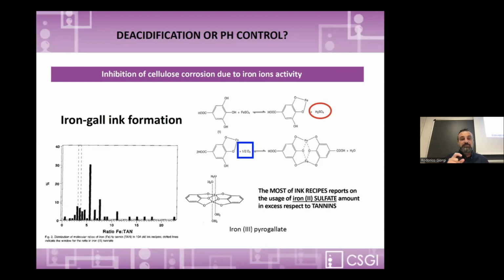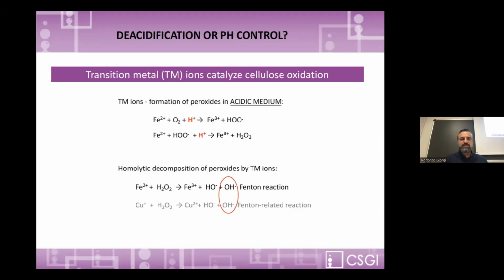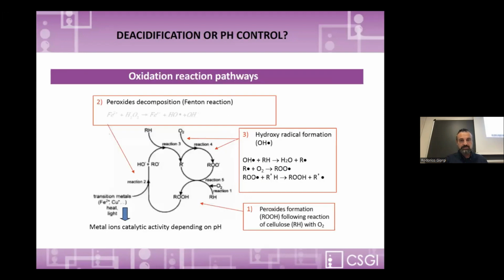This means that we have a lot of free iron ions, which unfortunately, under normal condition and in acidic environment, leads to formation of peroxide. And the presence of peroxide in situ produces, due to the well-known Fenton reaction, hydroxyl radicals. The presence of radicals creates very strong oxidation of cellulose, and we have the starting of a process that is autocatalytic, because we go into this loop and we cannot escape unless we are able to inhibit, to stop some of this reaction.